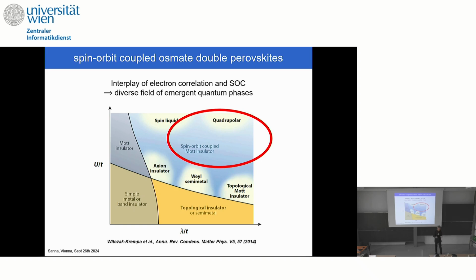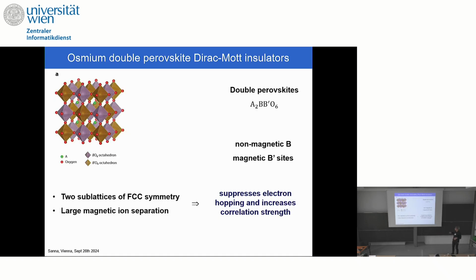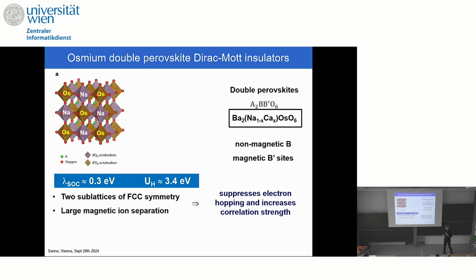Because this typically does not happen when you go through the periodic table, because typically when you increase the size of the ion, you are increasing the spin-orbit coupling, but you are decreasing U. But because of the double perovskite structure, as you very well know, we can see this also very naively from the chemical point of view, large magnetic ionic separation, and so the electron hopping is suppressed, and the correlation strength increases. So this is a very nice material to study what happens when these two energies are competitive with each other, and none of them can be considered negligible.